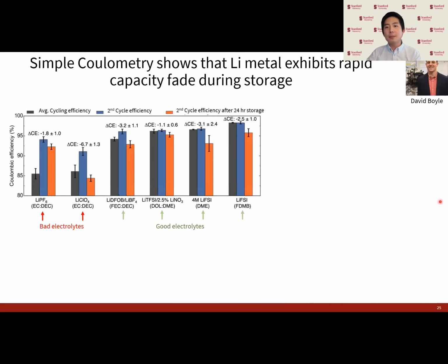So in collaboration with David Boyle, another student in our group, what we did is a fairly simple measurement of the capacity loss of lithium metal during storage. So across a variety of different lithium metal electrolytes, some of which are good at cycling, including this FDMB electrolyte and this dual salt electrolyte shown previously, and some which are bad at cycling, such as these more primitive carbonate-based electrolytes without any FEC additive, we measured the cycle efficiency of all these different electrolytes on the second cycle with and without a 24-hour storage step in between.